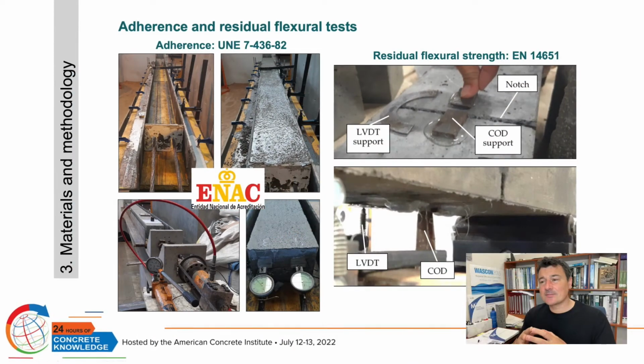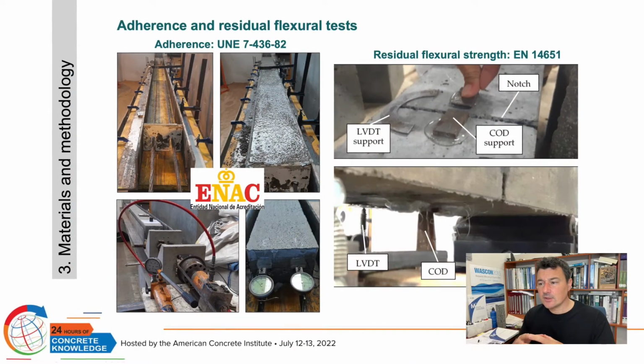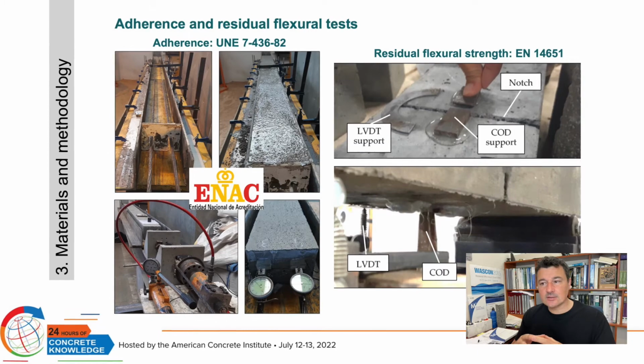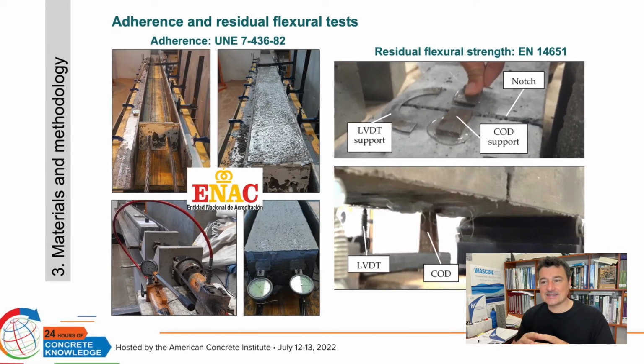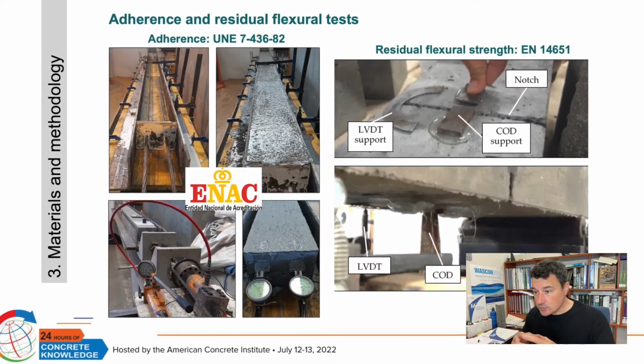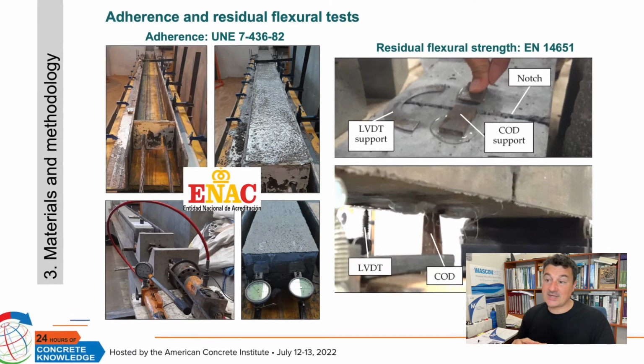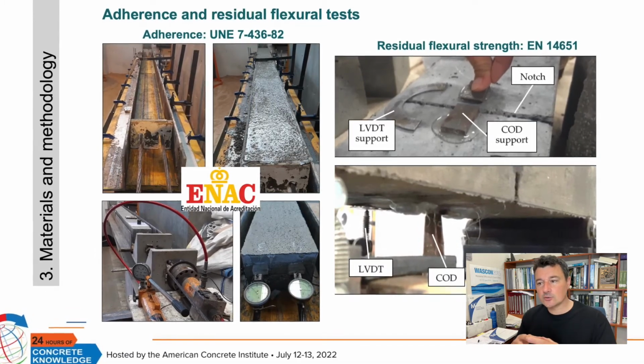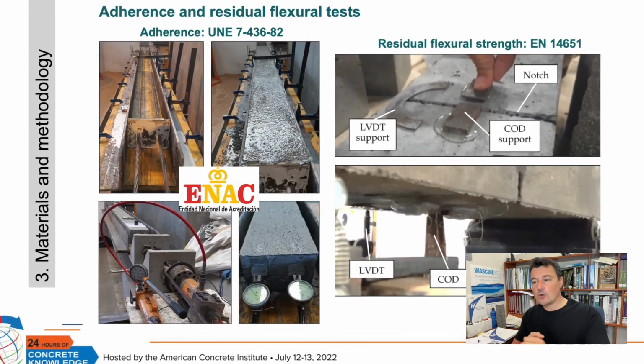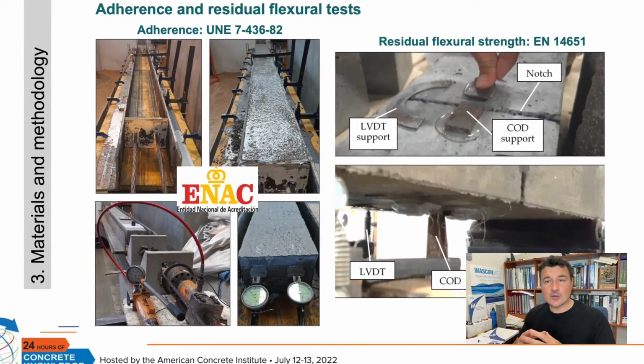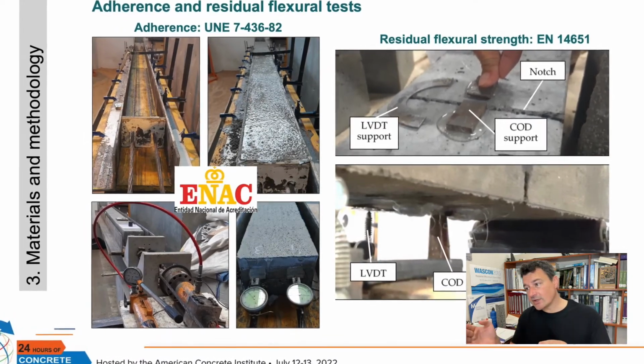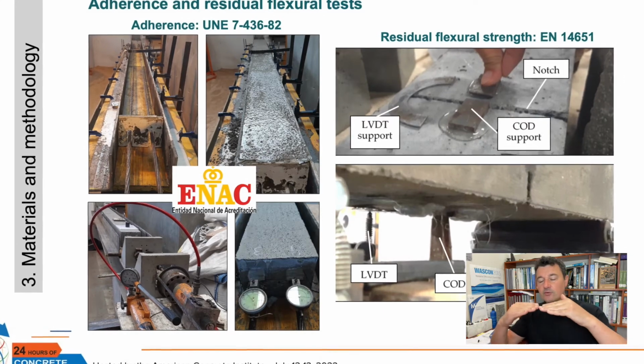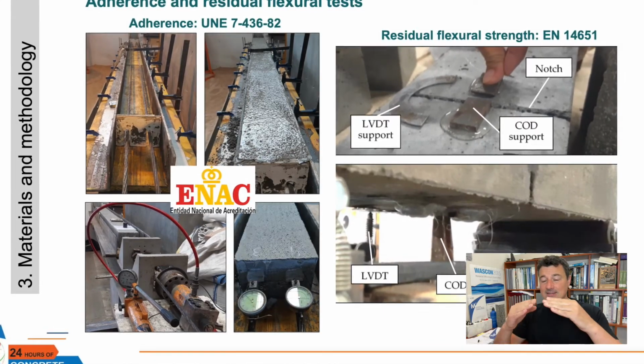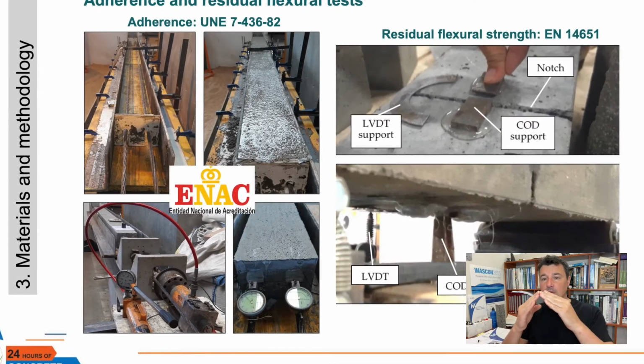Other tests performed on hardened concrete were the adherence and residual flexural tests. In this case, we use cores in pre-stressed conditions in order to determine the adherence of the siderurgical aggregate concrete. And also, we determine the flexural strength using three points and analyzing how the fissure opening behaves.